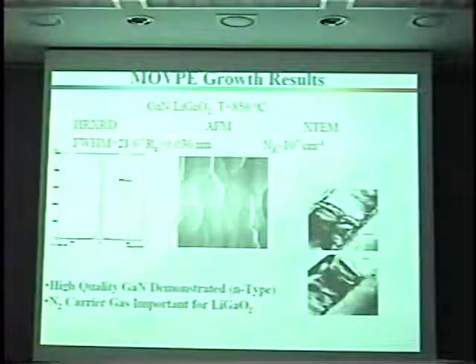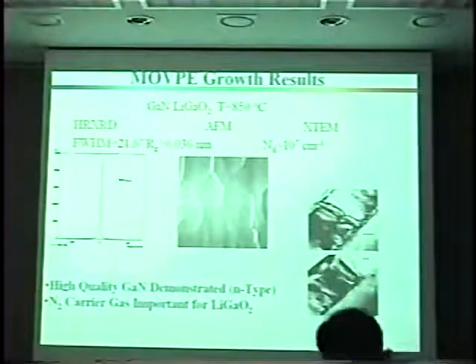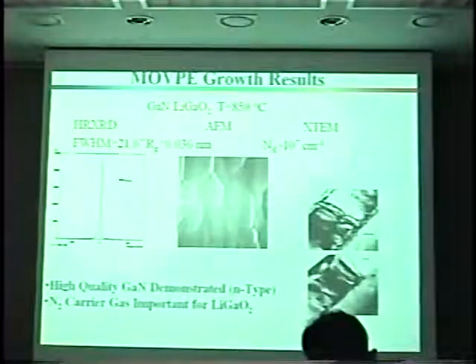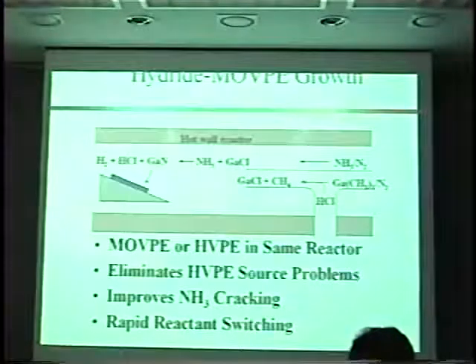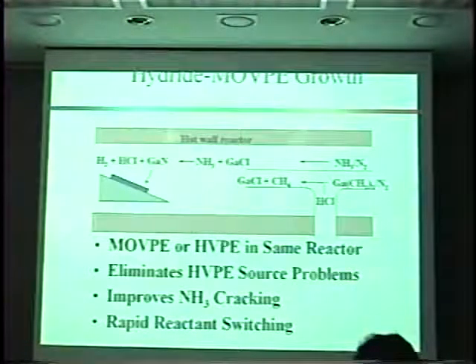And so here's a low resolution TEM micrograph showing the cross section. We had to look pretty hard to find a few dislocations. Next job then was to grow a very thick gallium nitride, in the order of about 200 microns. We did this using hydride VPE, but a redesigned one.